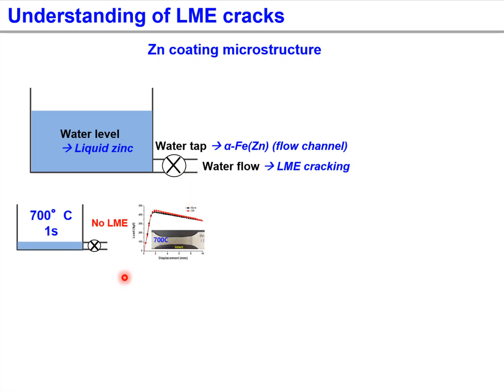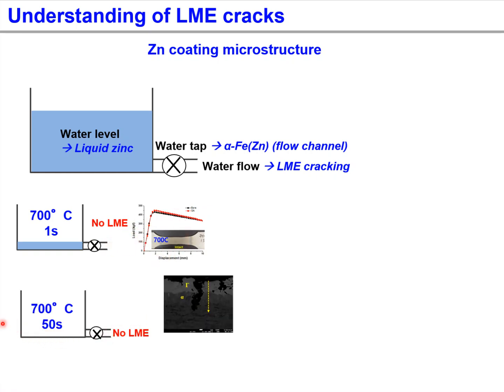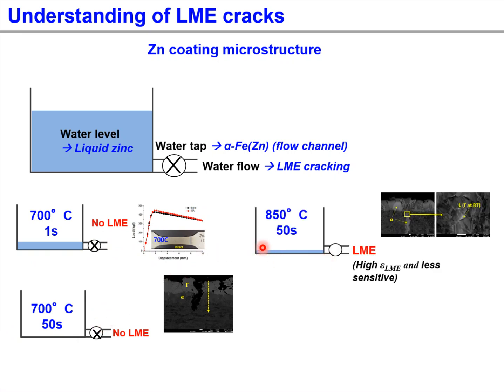At 700 degrees Celsius with a 1 second hold time, due to the very small amount of liquid zinc and the continuous alpha Fe layer, there are no LME cracks. Same for the 50-second hold time condition. However, at the higher temperature of 850 degrees Celsius with the 50-second hold time, both the liquid zinc and the breakage of the alpha layer end up with LME cracks.